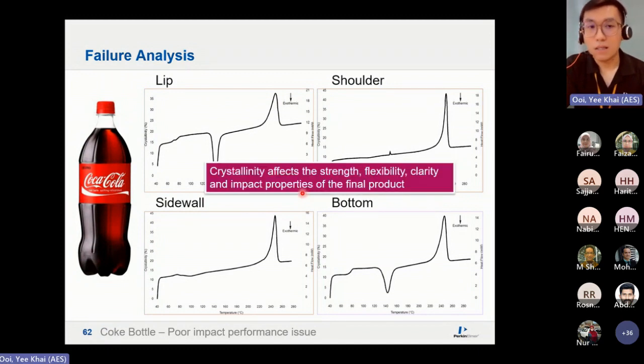So they investigate what is actually happening to the bottles itself. We sample different parts of the bottle: you have your lip, your shoulders, your sidewall, and your bottom. We noticed that the sidewall and the shoulder, this whole part, is actually very crystalline. You can see, okay, it's very crystalline.